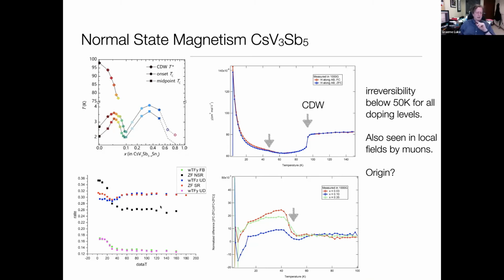We went and looked back at some very careful muon spin relaxation measurements as well. The measurements of the superconductor are all done to the left of about 5 Kelvin, so just at low temperatures. But what we see is a change in the relaxation rates, which tells us about the field distribution that the muons are detecting, also happening around this 50 Kelvin point. So there is some magnetic behavior happening in this material. It's extremely weak. We're looking at perturbations on essentially the fields of the strength of the nuclear dipole interaction.